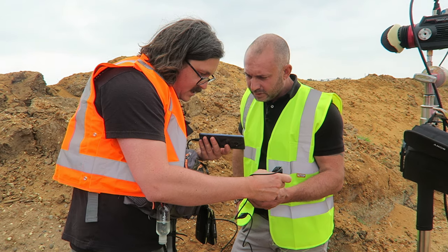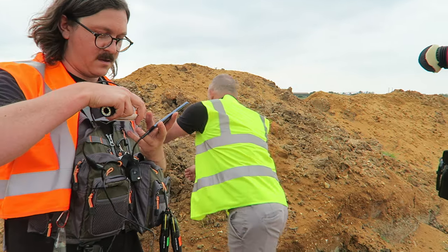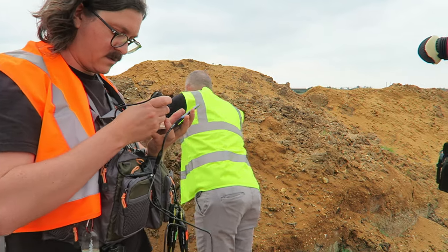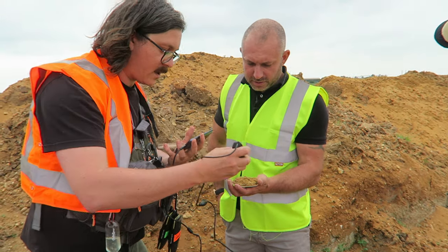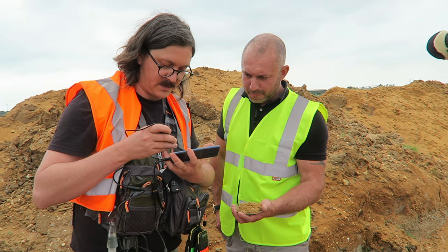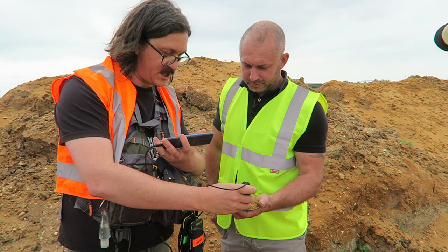In my Mary Poppins bag here, I've brought a microscope. You can see here how fine the particles are and how round they are. To me they still look quite jaggedy. Have you got some normal quarry sand as well? Yes — let me have a look at that. Here we go — this is some of our mineral that we're excavating. You can see the difference: there's obviously stone in there and it's much coarser and more angular. The difference is now apparent — the desert sand grains are like little ball bearings compared to this which is granular and jaggedy like sugar.